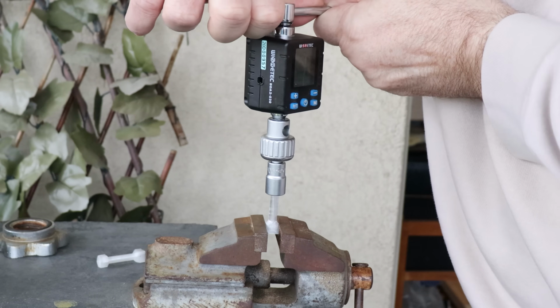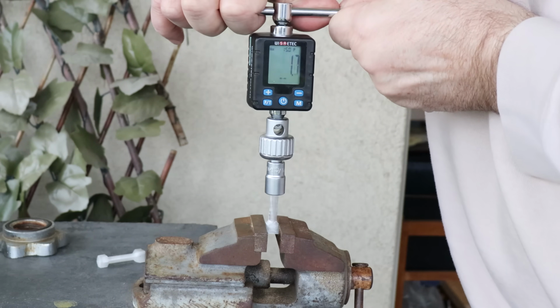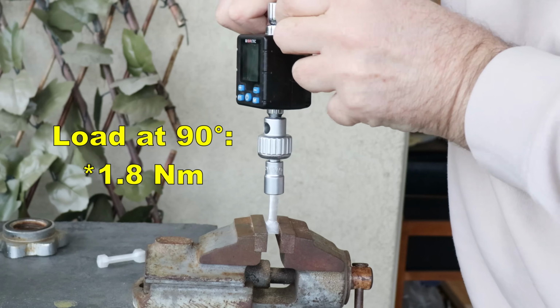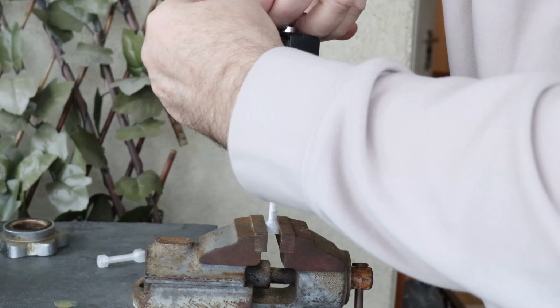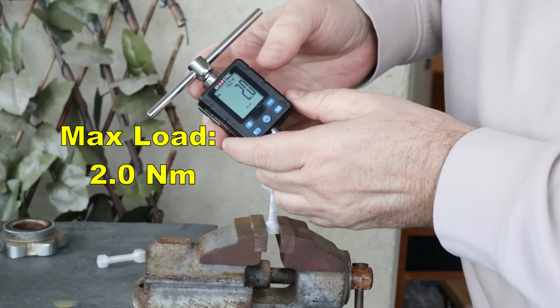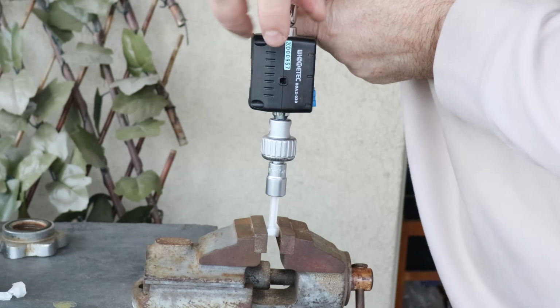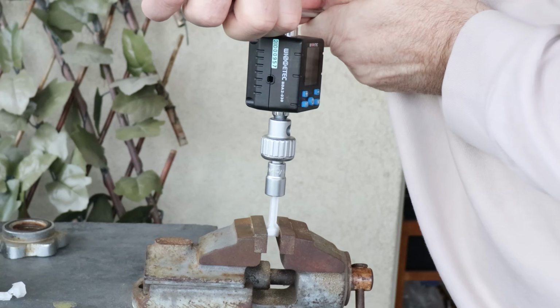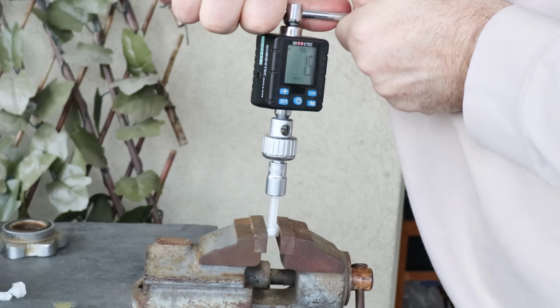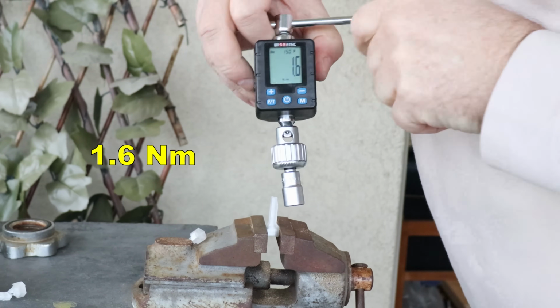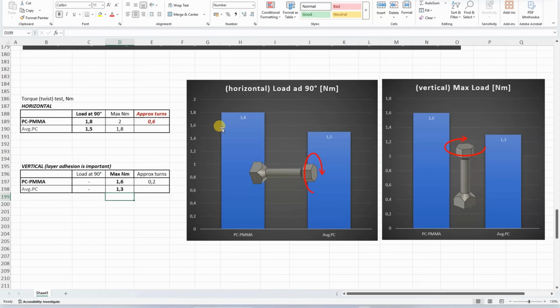Torsion test starting with horizontally printed part. 1.8. Printed in vertical position. 1.6. These are great values, and in both cases it was stronger compared to the average polycarbonate by approximately 20%.